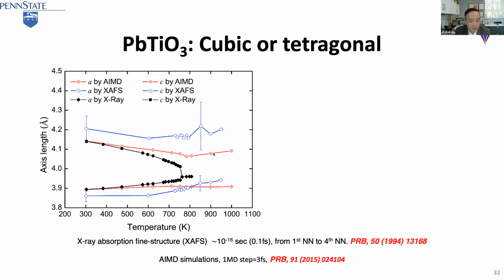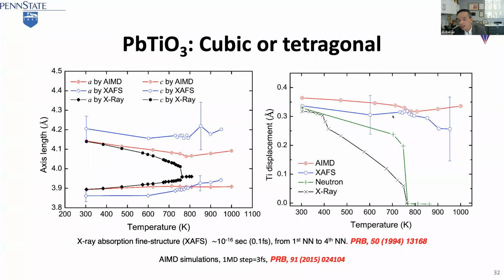The red line is our prediction because we use the experimentally measured lattice parameter. The beginning is tetragonal, and it becomes cubic by experiment. But when I look at the individual atoms, it's still tetragonal. Okay, it also has a polarization. This agrees perfectly with the high resolution experiments.